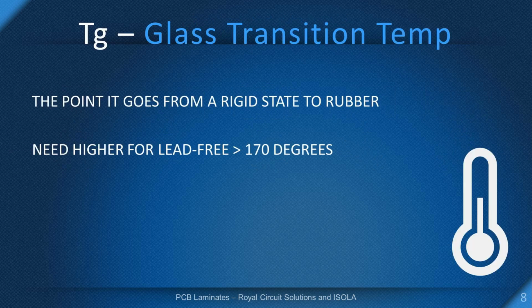All right, so the first one we're going to discuss is our glass transition temperature, which, as many of you know, is when our resin actually changes from a rigid or glass-like state to more of a rubbery part. With the introduction of lead-free assembly, we've really had to increase all of the TGs of the resin types to accommodate the solder that we're using for this. So our minimum for a lead-free is going to be around 170 degrees. When we go and look at our different polyimide materials, they're going to be even much higher than this.